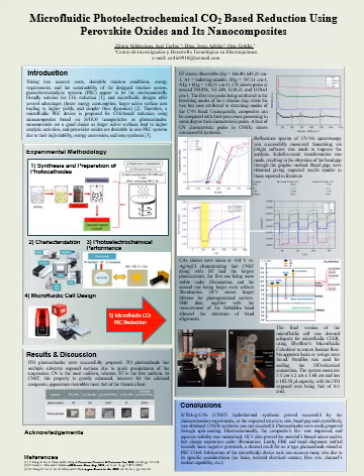After this, other characterization methods followed. In this case, we can see the UV-Vis reflectance spectra after its transformation via the Kubelka-Munk method in order to extrapolate and obtain the band gaps of all of the materials. In this case, we can obtain the band gaps in order to observe light absorption characteristics, and also as a means to compare these light absorption characteristics with those reported in literature.